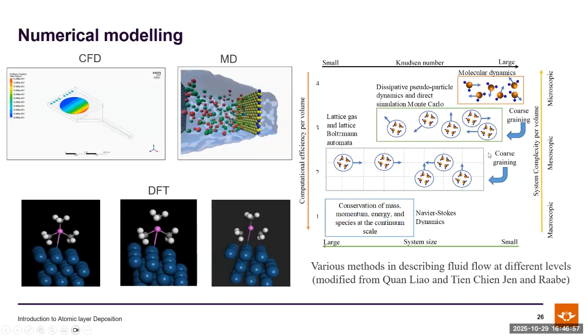And so this is one thing I always tell my students: before you go to that probe, if I want to deposit using ALD, and because all the ALD is very expensive, unfortunately, it's slow and expensive. This is the disadvantage. So I tell them that before you do that, go through your first intuition based on the DFT. So you can know from first principles whether your materials do work. And after that, we can go through the MD and CFD for verification.